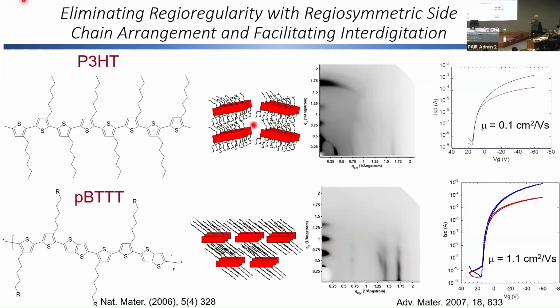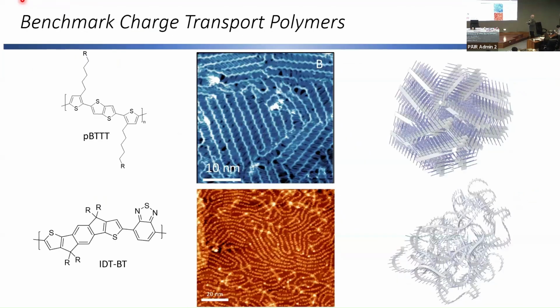And we can see whereas the best P3HT thin film transistor carrier mobility, when you extract the mobility from these transfer characteristics here, the highest mobility we were typically achieving with P3HT was 0.1. But whereas when we take a very similar polymer backbone, but now introduce this side chain interdigitation to reduce energetic disorder, we're now able to get to carrier mobilities of an order of magnitude higher. So now much, much higher in performance. So we were quite pleased with that. So this was our PBTTT.